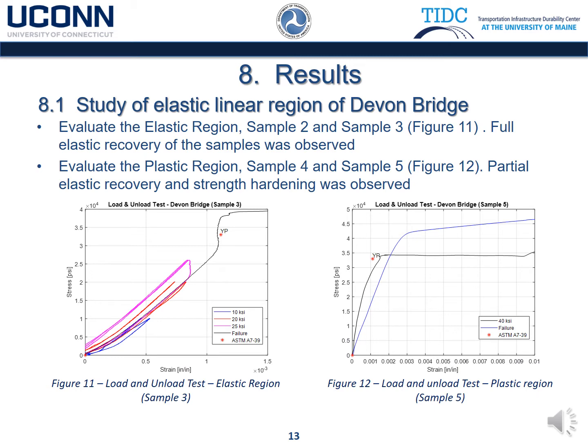Results. Study of the elastic linear region of Devon Bridge. Sample 2 and sample 3 were loaded and unloaded using different test rates and stress levels within the elastic region through failure. Figure 11 shows the stress-strain plot of sample 3, where we can see the load path for 10 KSI, 20 KSI, 25 KSI, and failure.